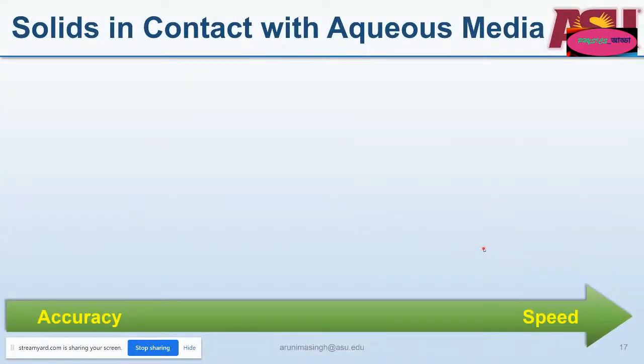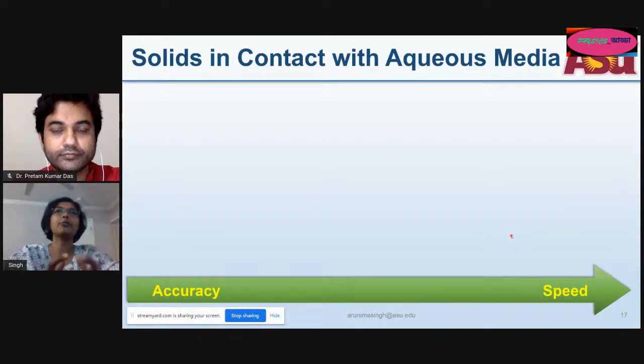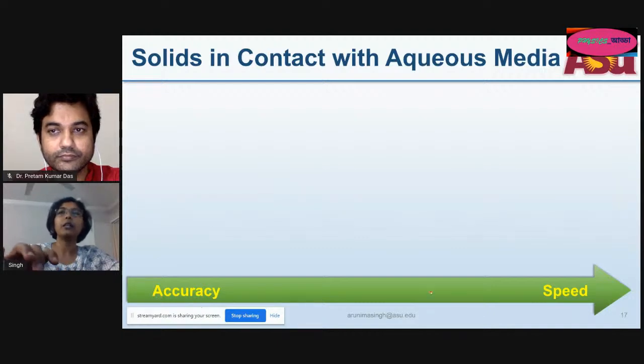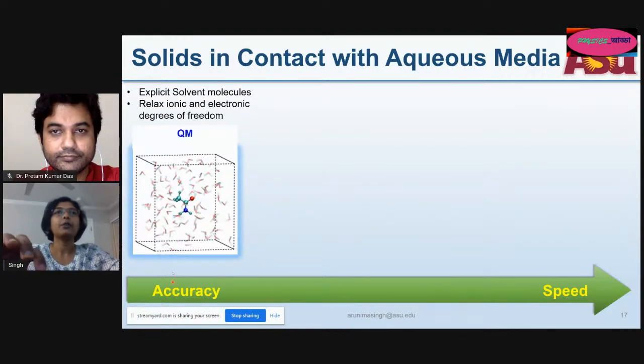If you look at the methods out there to assess the reaction or the performance of materials, solids, which are in contact with aqueous media, I plot them here on this slide, with the ones on the left-hand side being highly accurate but highly expensive, and ones on the right-hand side being quite inexpensive and fast, but their accuracy is compromised. So at the very left, we have very accurate quantum mechanical simulations where we do explicit calculation for the solvent molecules, such as the water molecules shown here, and your system in consideration, and you relax the ionic and electron degrees of freedom. This is very, very expensive because the configurational entropy of your solvent molecules is enormous, and it's not possible to capture that.